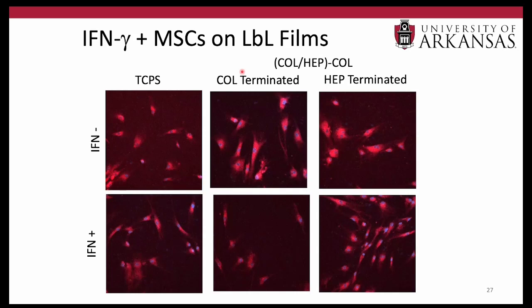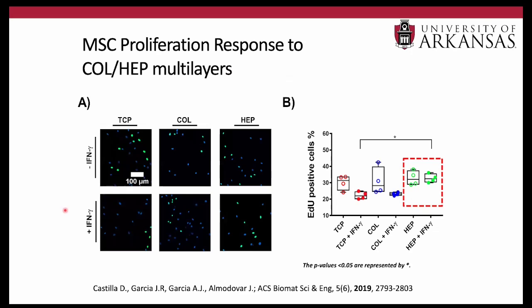So again, first starting off with just looking at cell morphology. Basically, we see no difference in the presence or absence of the cytokine IFN. Cell morphologies, they look pretty good. Then we investigated proliferation, and here's where we start to see some interesting behavior. When we expose the cells to the IFN on our control polystyrene surface, we actually see a decrease in proliferation. And so that's not ideal, right? So if you're manufacturing the cells and you want to treat them with these proteins to enhance their therapeutic property, you still want them to grow, right? And so you don't want their proliferation to decrease.